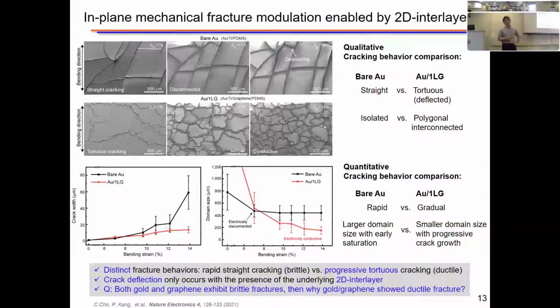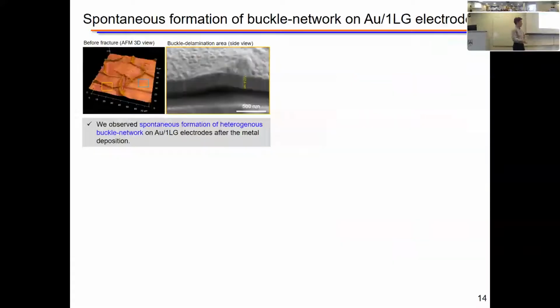This motivated us to look into the strain-dependent electrical performance, which I'm going to talk about in a later slide. But here, we observe a distinctly different fracture behavior with the underlying graphene layer. This raises a very interesting scientific question. From previous studies, we learned that both metal and graphene show relatively brittle fracture behavior. But when we layer these two materials, they show relatively ductile fracture behavior, indicating that there must be an external mechanism playing a role in this phenomenon.